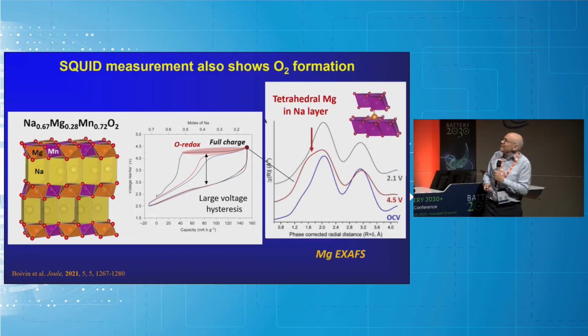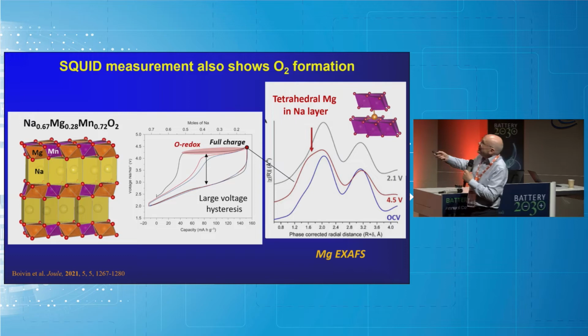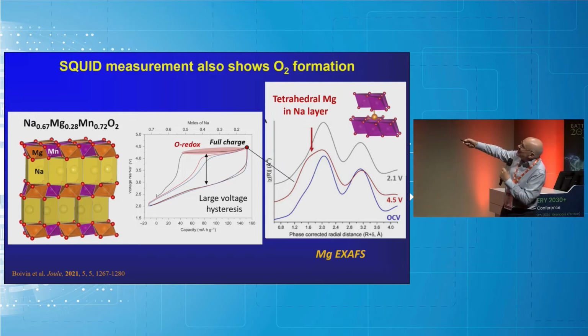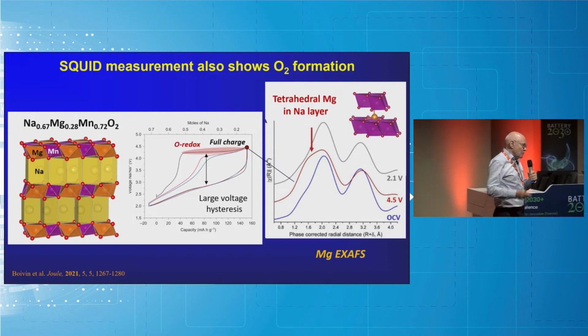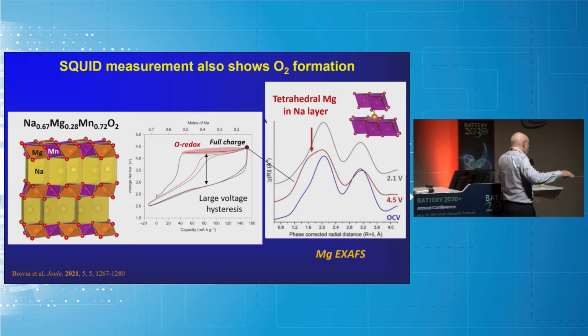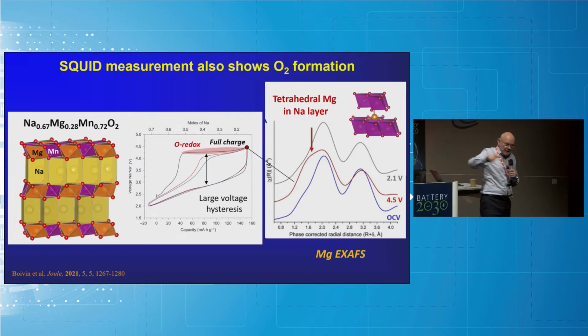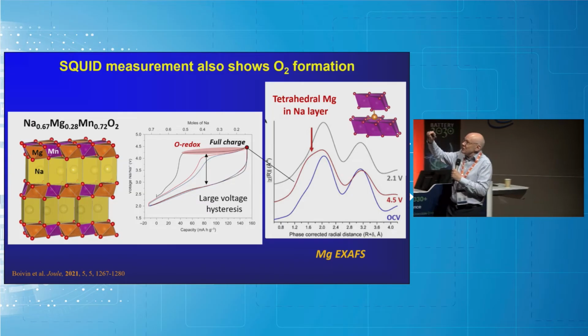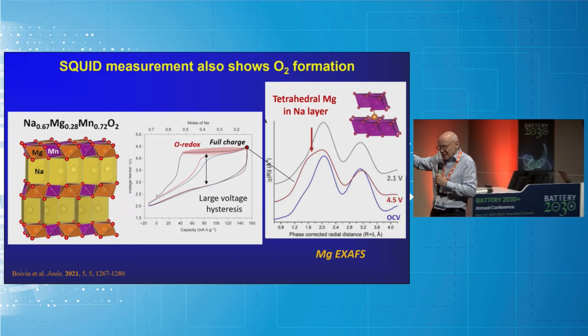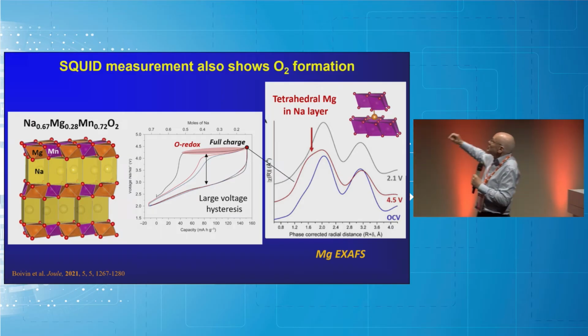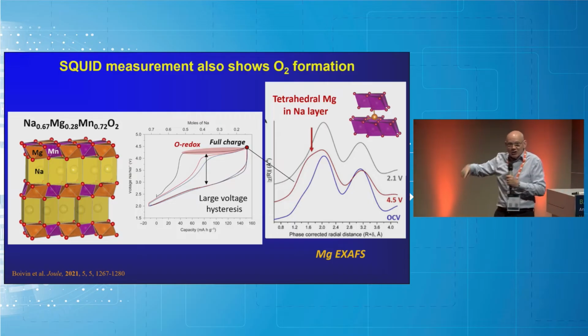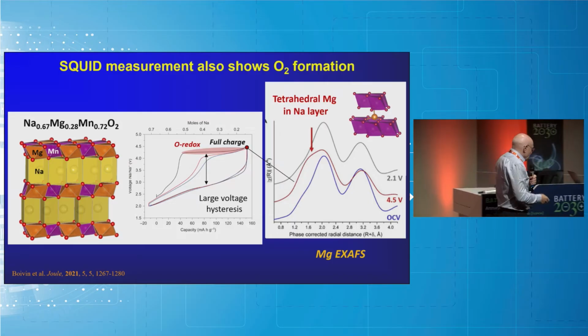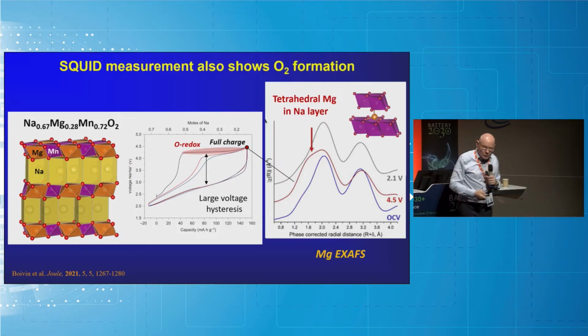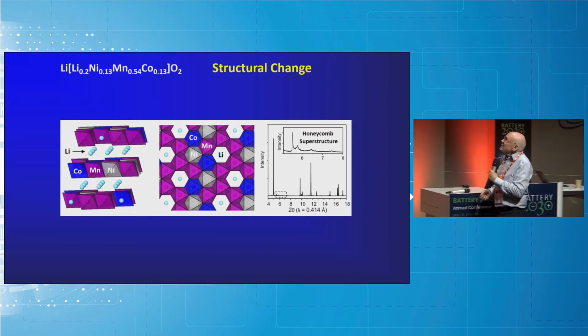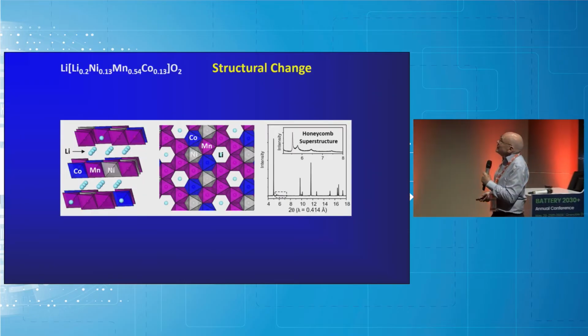Okay, and this is, by the way, why this happens here. It turns out the magnesium does move out of these layers. When you take sodium out, you go from the P to the O stacking, the octahedral stacking. Magnesium actually drops from the transition metal layers into tetrahedral sites when you charge, and that's what allows the reorganization that I'll show you in a moment that has to happen to form and trap O2. So let's come to how this O2 process can occur.